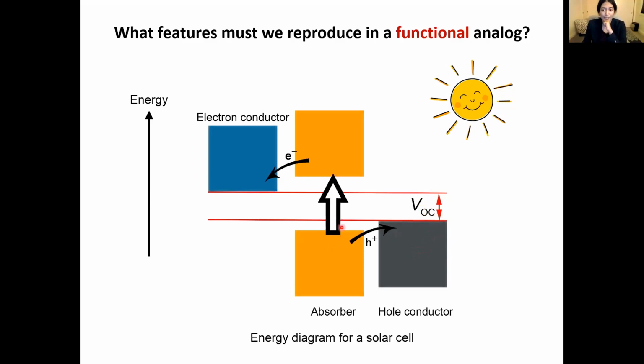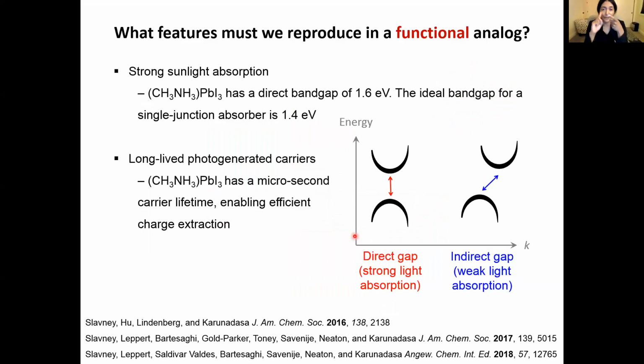So I want a material that absorbs sunlight very strongly and very, very efficiently, promotes an electron from my filled bands to my empty bands. And then I don't want that electron to just pop right back down, because nothing happens then except I get light. Instead, I want the electron and the hole to hang around for long enough and diffuse through the material and find the current collector, the electron conductor and the hole conductor. So what do I want in my solar absorber? I want a material that absorbs sunlight very efficiently. And I want a material where those carriers, the electron and the hole that I mentioned, hang around for long enough and are mobile enough that we can get current out of the electron and the hole.